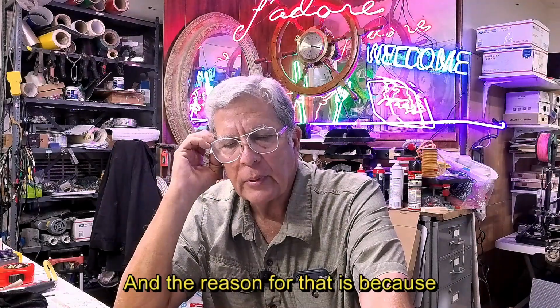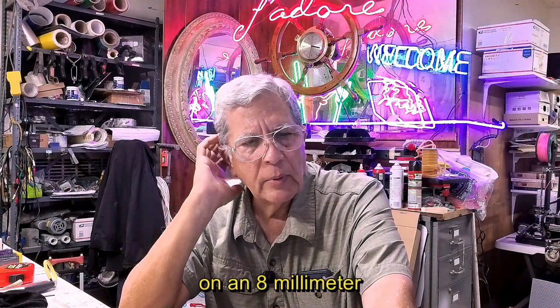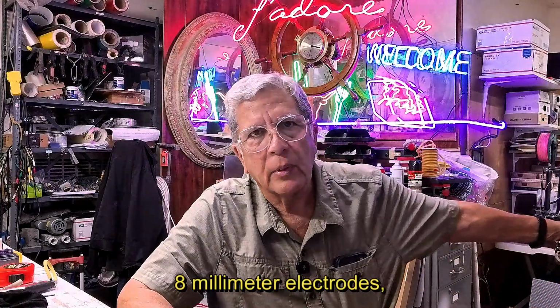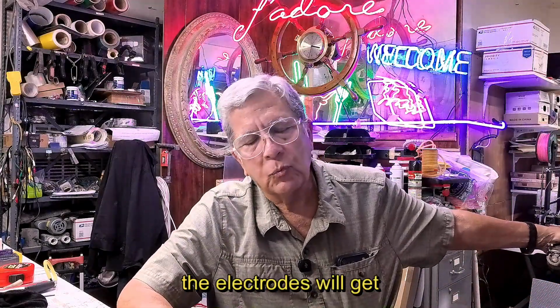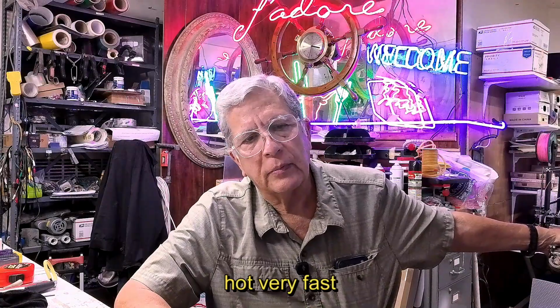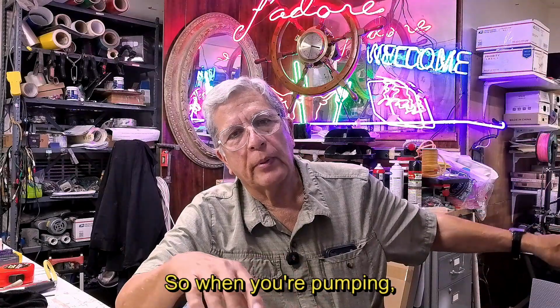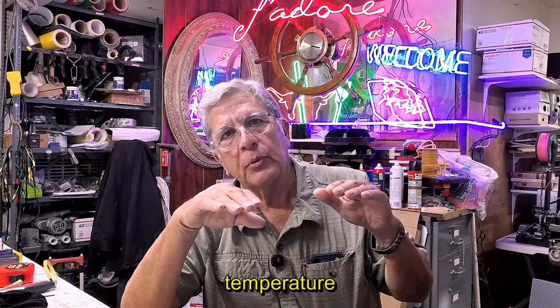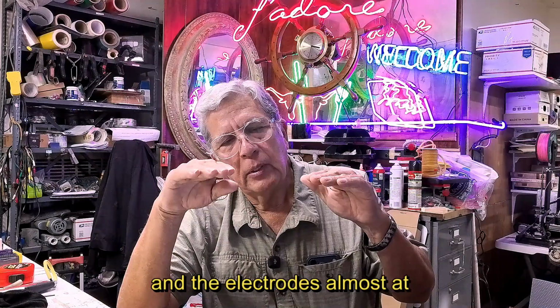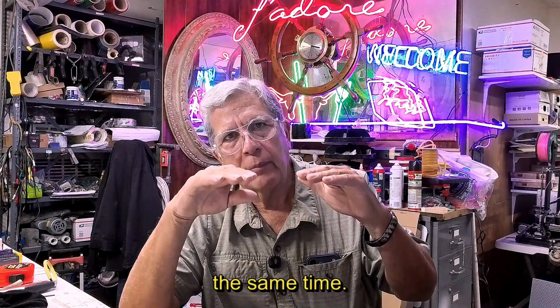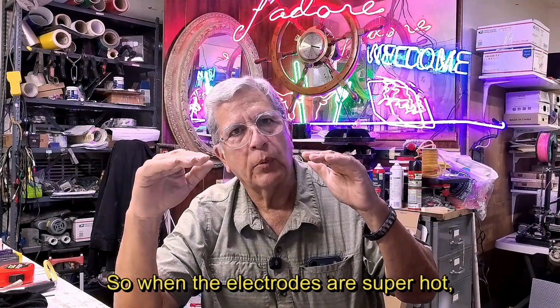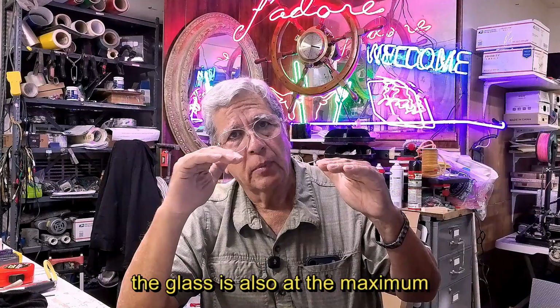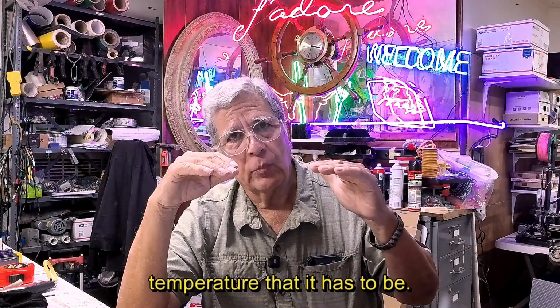And the reason for that is because on an 8 millimeter unit, if you put 8 millimeter electrodes, the electrodes will get hot very fast and the glass will not. So when you're pumping, you have to bring up the temperature of the glass and the electrodes almost at the same time. So when the electrodes are super hot, I mean it's completely orange, the glass is also at the maximum temperature that it has to be.